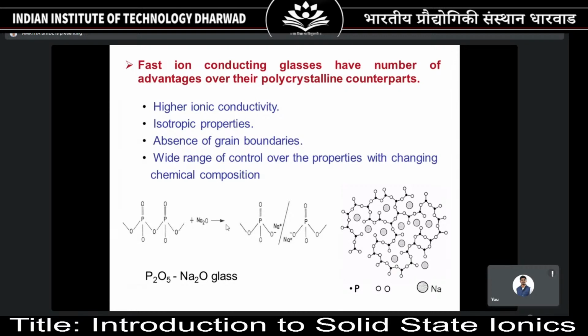Glassy electrolytes exhibit high ionic conductivity compared to crystalline materials. They have isotropic properties, absence of grain boundaries, wide range of control over properties with changing chemical composition. I'll come to that changing chemical composition slightly later. But this is what happens. A phosphate chain interacts with the sodium oxide. They are broken. And whatever periodicity you had earlier is broken, and you can get open space. See, this sodium ion is free to move everywhere, wherever there is a vacancy to travel within the glass. So that makes a better environment for the ionic motion.